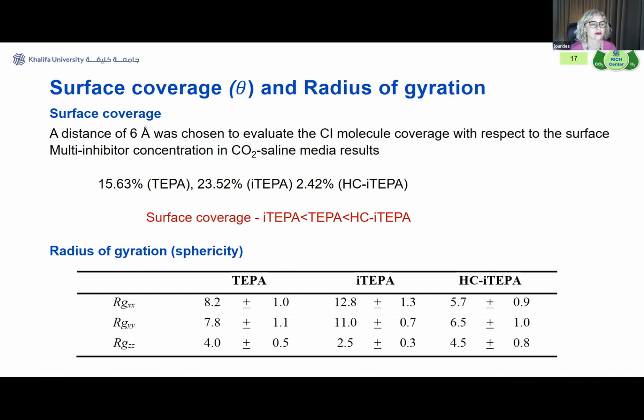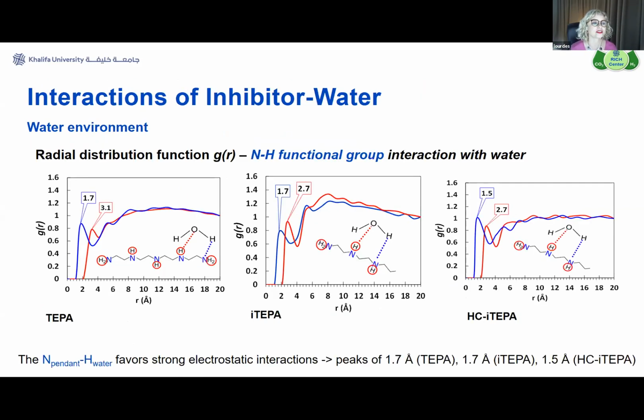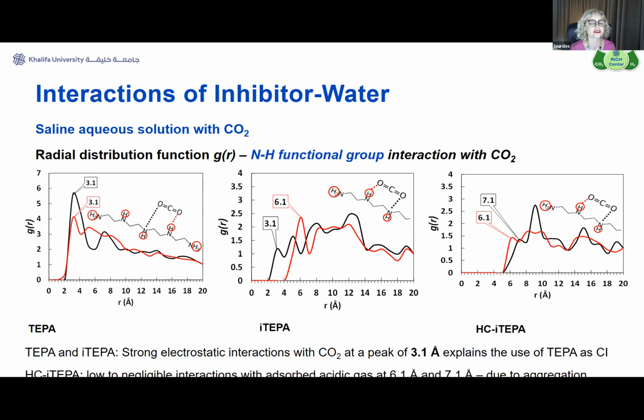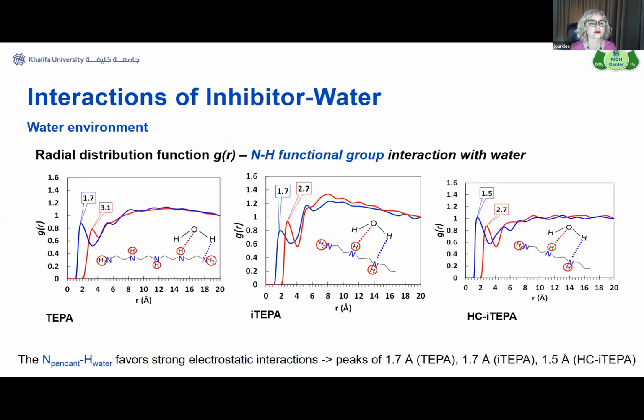And we also calculated the radius of gyration, and what you can see from the numbers here, when you compare the XX, YY, and ZZ direction, is that the iTEPA molecule is stretched, forming this film covering the surface. We have also studied the radial distribution functions to further investigate this. And then it depends if we have just water or if we study the solution with the molecules.